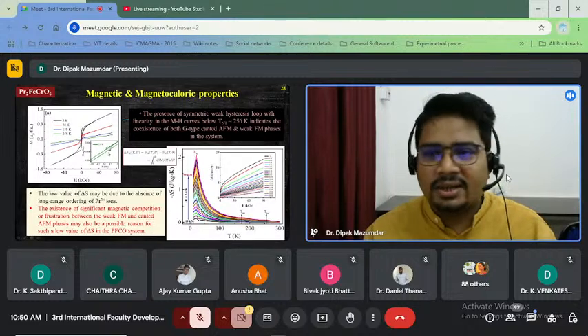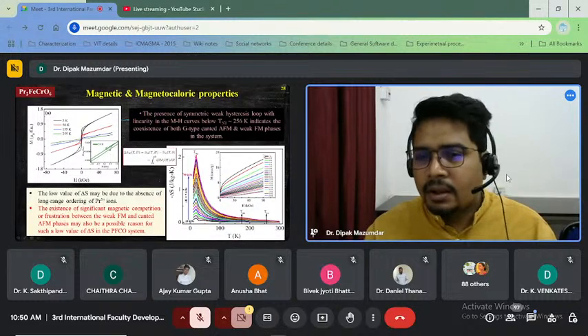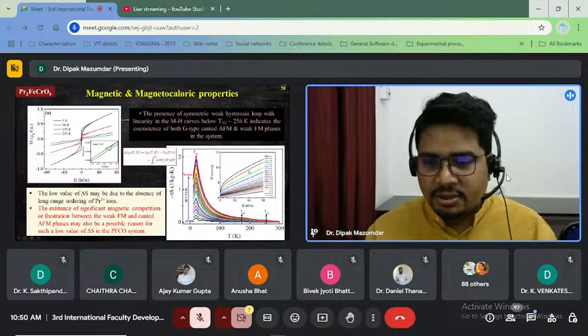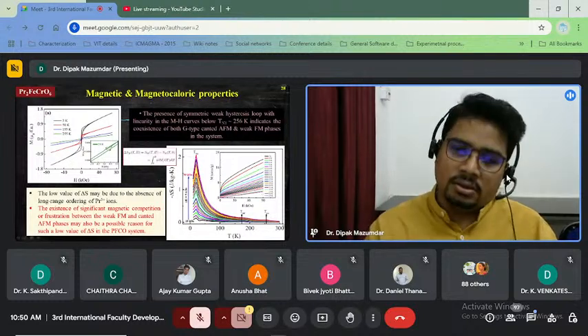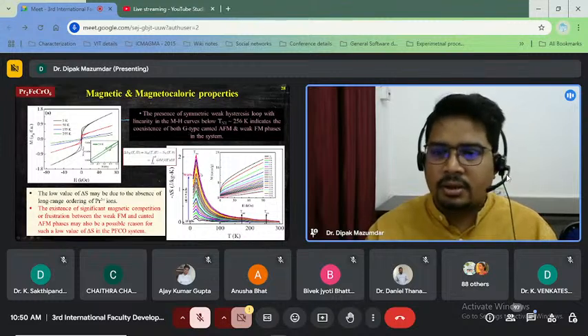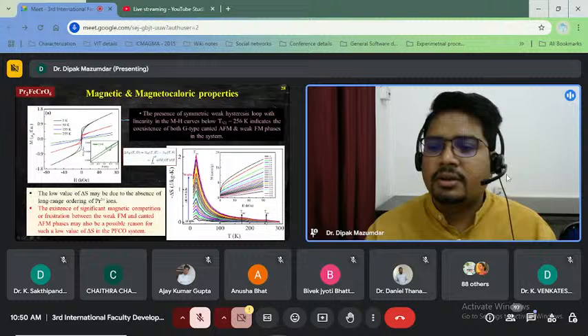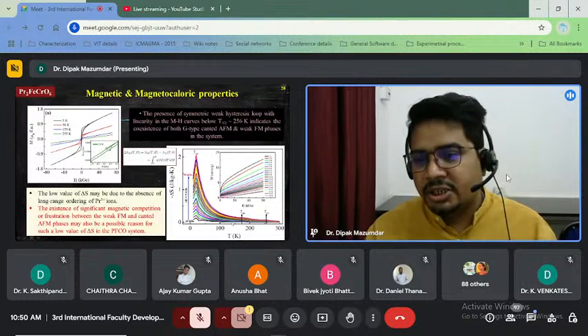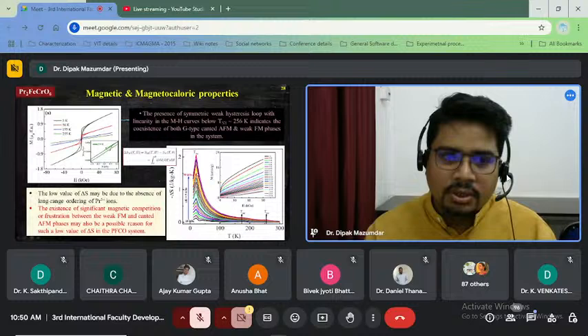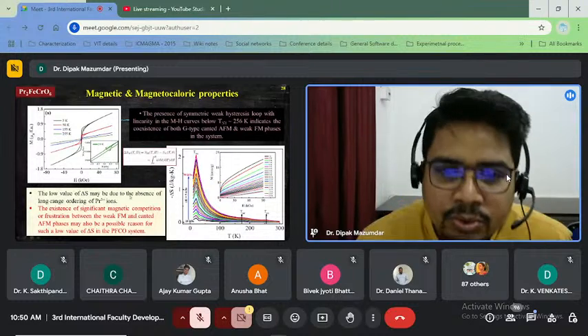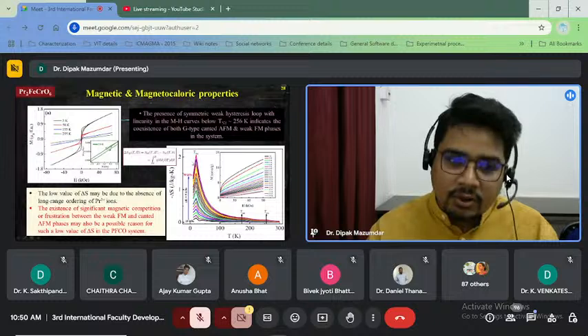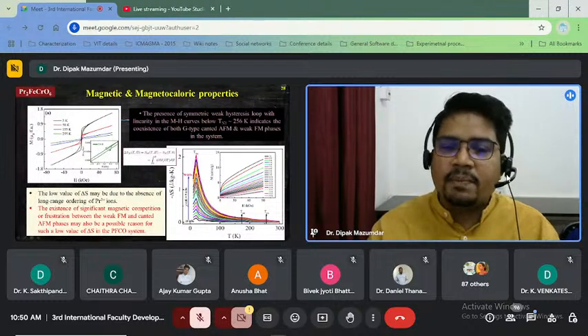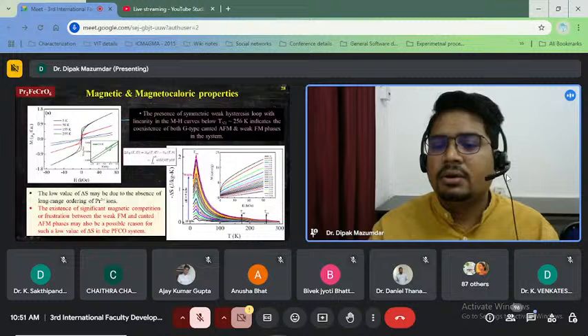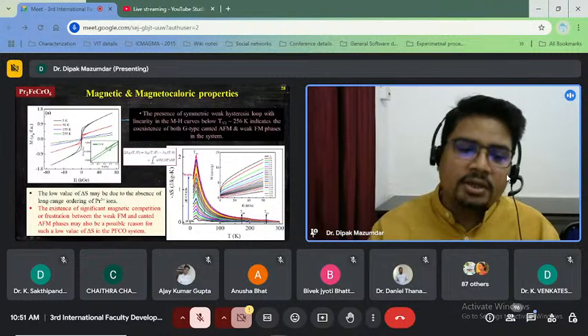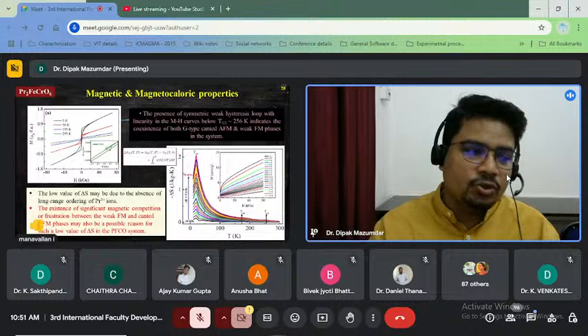Then I calculated the magnetic entropy change data by taking the isothermal magnetization at different temperatures, and this is the calculated entropy change data, where we can observe the mentioned transitions of this compound. So this low value of delta S may be due to the absence of long range ordering of praseodymium ions, and the existence of significant magnetic competition or frustration between the weak ferromagnetic and canted antiferromagnetic phases may also be a possible reason for such a low value of delta S in the PFCO system.